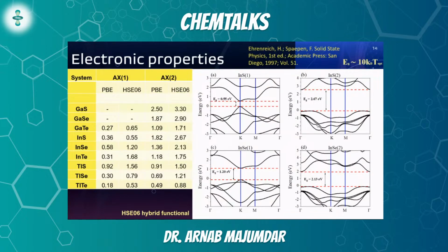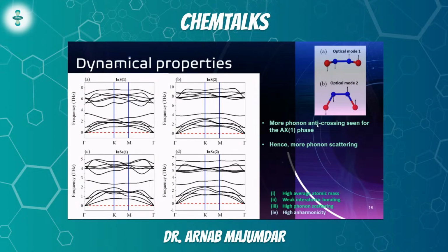Okay. This slide depicts electronic properties, the electronic band structure, and I've tabulated the electronic band gaps as well. It doesn't affect our thermal conductivity much, but just by looking at the graphs, we can have a pretty good hunch that from the band gaps, we can predict that at slightly higher temperatures, we might be able to use these materials as pretty efficient thermoelectric materials. I'll not spend much time on this, but all the calculations were done using both PBE and the hybrid functional HSE06.